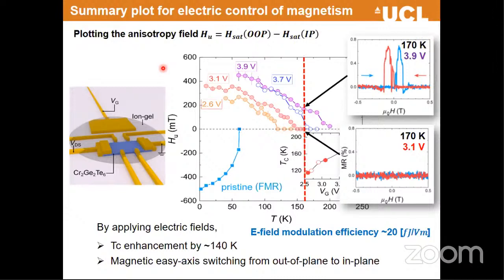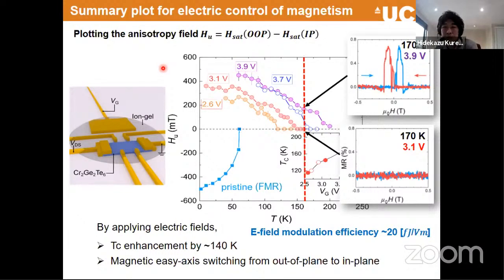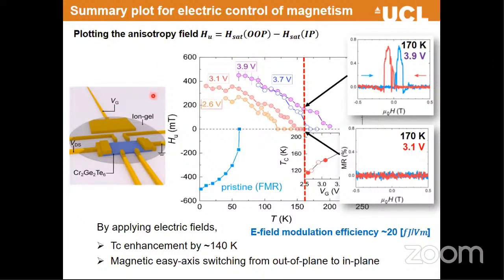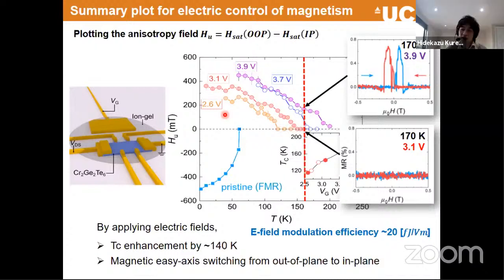Is this strong in-plane anisotropy already in a very conducting metallic state, or is it still in a relatively insulating regime? Because if it's insulating, then I could imagine, for example, that you create something like localized chromium 2+. It may behave differently from normal 3+. Normal 3+ have practically no single site anisotropy, very isotropic. 2+, I don't know, but couldn't it be that single site anisotropy starts to play some role in the doped material? Sure. I don't see it right away, but it might be an option.